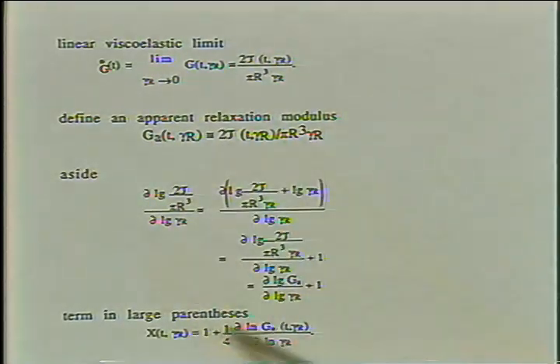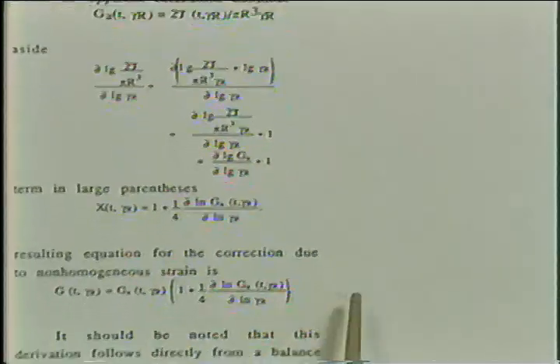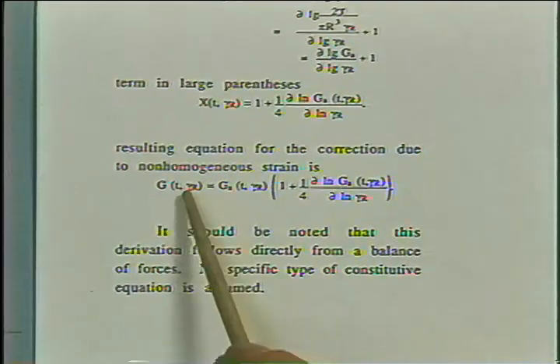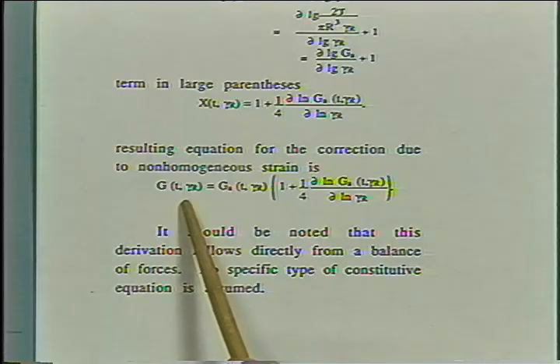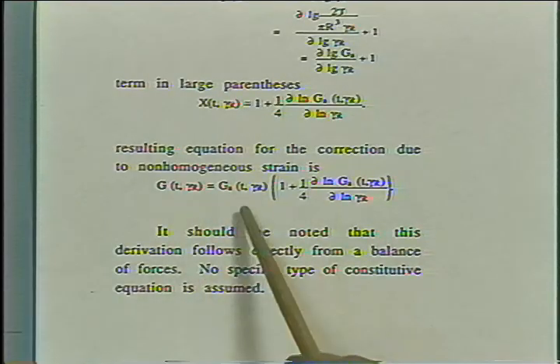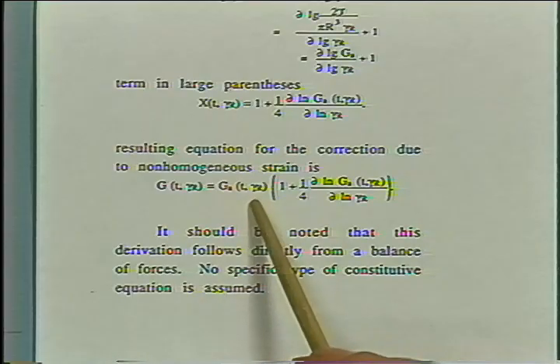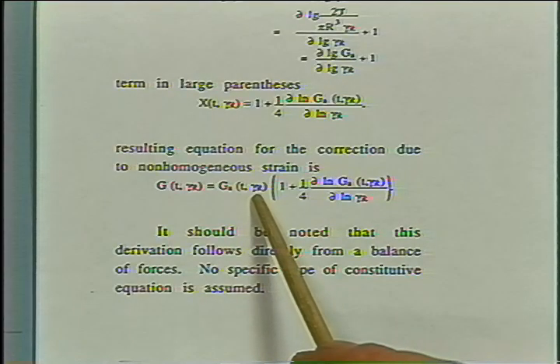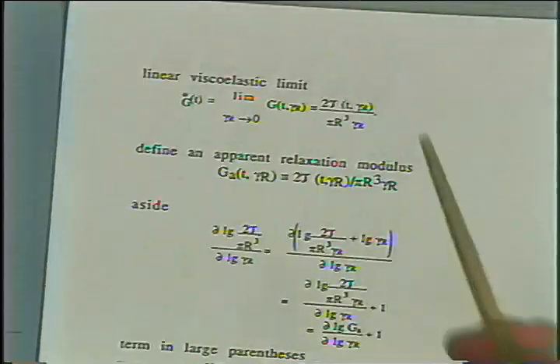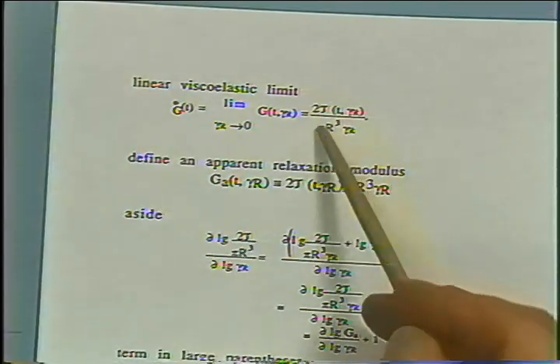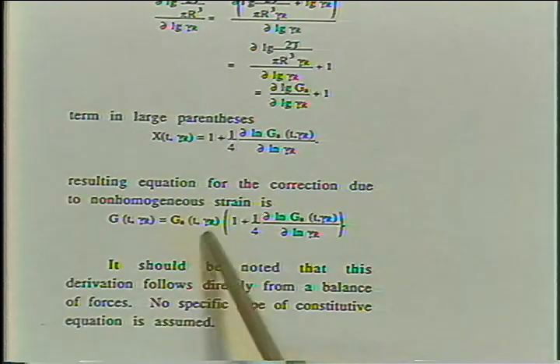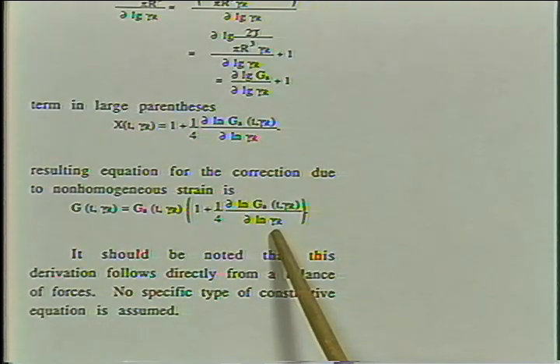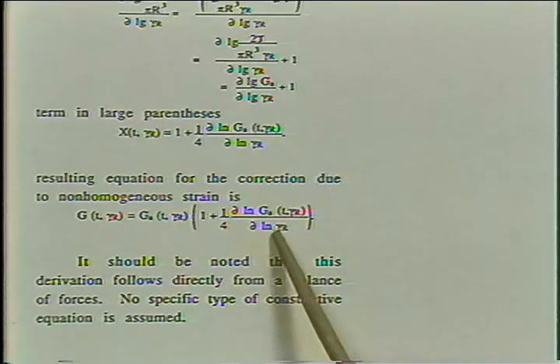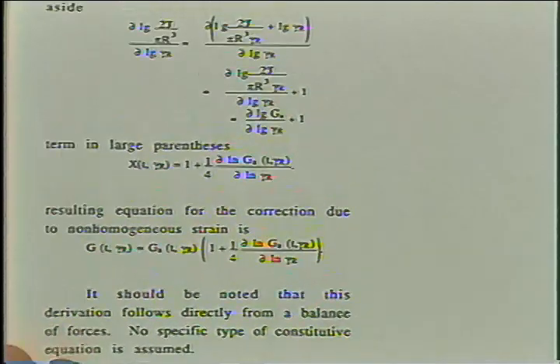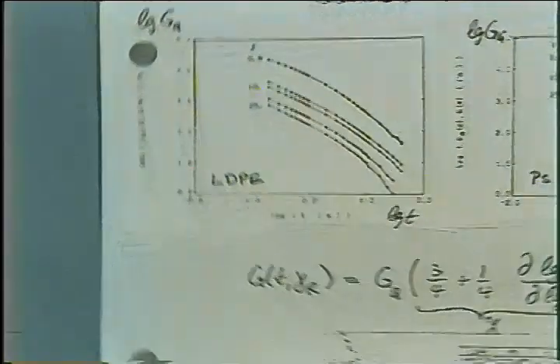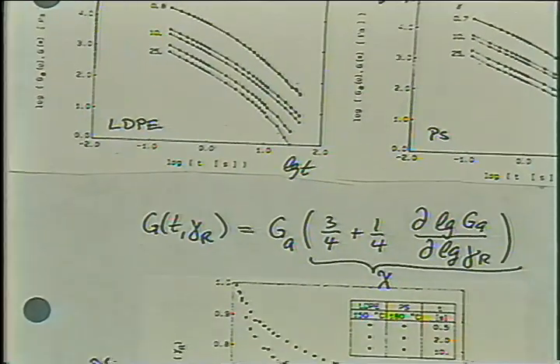You can rearrange all those equations, and you find now, this was Soskey's result. He finds the relaxation modulus. That's what you saw in Osaki's plot. Given as the apparent modulus, that's what the rheometer gives you as a result. From the torque, the rheometer normalizes everything with the geometry, and it gives you the apparent modulus. And you measure that at different strains, and then you get this gradient here in this function, and you get the total result.